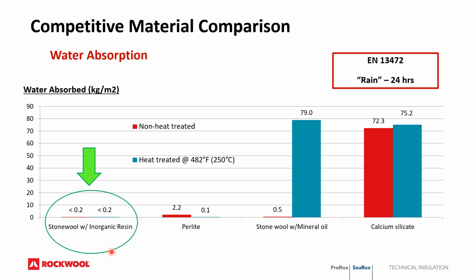For this comparison, we use the EN 13472 test, which is a partial submersion test of our insulation for 24 hours. That's meant to simulate short-term water exposure like a rain event, and water absorption is measured in the weight of water per submerged area, kilograms per meter squared. And as you can see, stone wool treated with inorganic resin, right here, performed well with less than 0.2 kilograms per meter squared before and after heat treatment, similar to perlite, which also had a low amount of water absorbed.